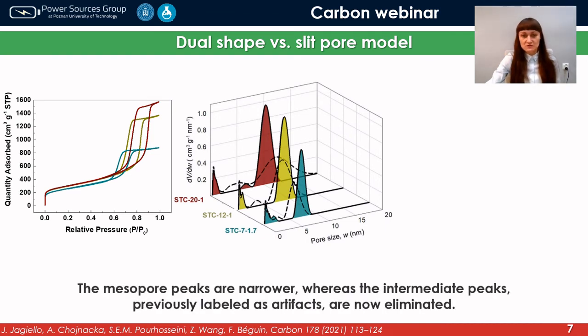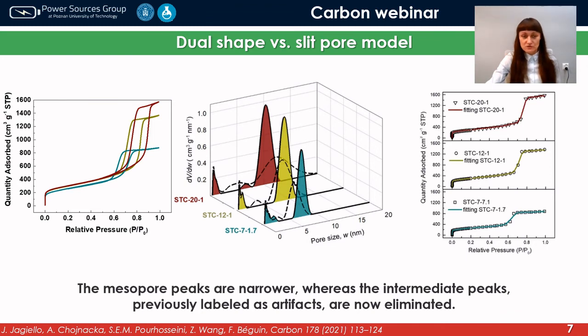What is interesting is that the micropore region is the same for both applied methods, because we are using the same adsorption range to calculate the micropores. However, for the mesopores, we found much narrower peaks when applying the dual shape method, and additionally, by using this method, we are able to eliminate totally these peaks which are labeled as artifacts. Moreover, by application of the dual shape method, we can see a perfect fit to the experimental data.